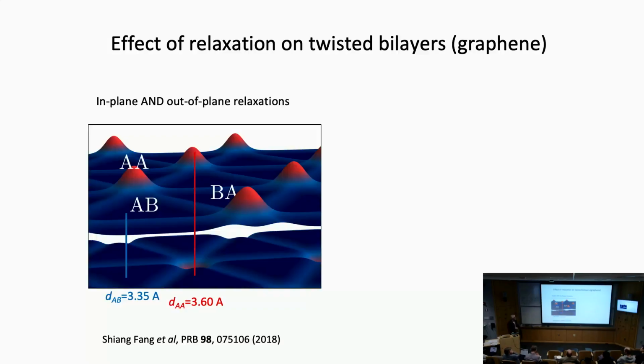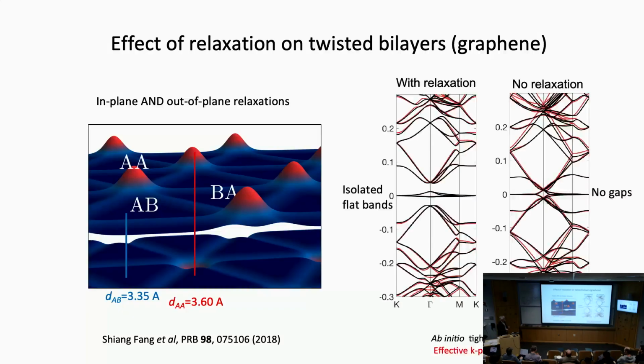So, putting the two things together, this is the atomic relaxation that I already told you about, seen here from a slightly different perspective. The dark regions are the triangles that I was mentioning, which are close to each other in distance, exactly the same as in graphite. The red regions are the AA regions, where the atoms basically repel each other because that stacking is energetically unfavorable, and of course there are the domain walls between. And the repulsion is quite strong. This change is about 10% in the distance, in the original distance between layers. And it has a big effect in the electronic structure.